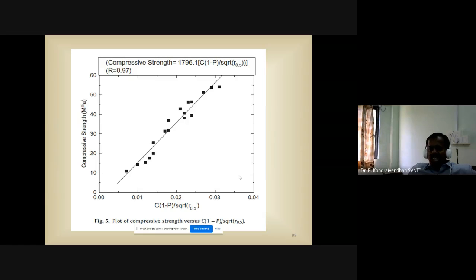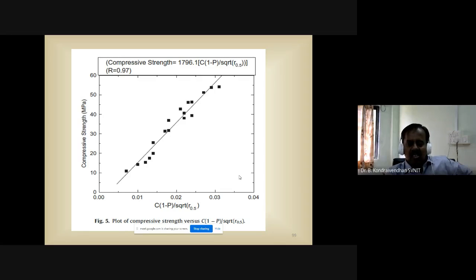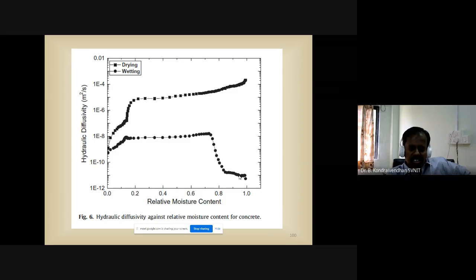As I mentioned earlier, sigma equals Kc into 1 minus p divided by square root of r.5. Here we should not use alpha. Alpha is applicable only in the case of paste and mortar. So directly you can determine the K value by using your compressive strength data versus C into 1 minus p divided by square root of r.5. That's how we calculated. So this K value is coming 1796.1.